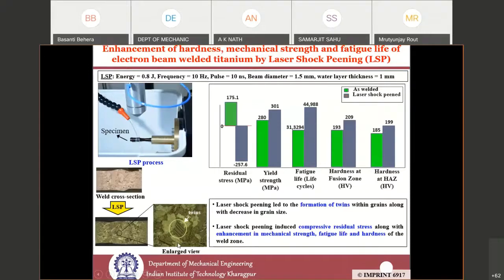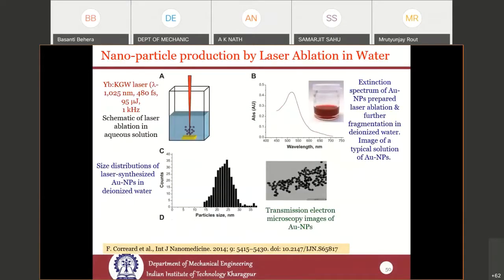Another interesting application of laser underwater is laser ablation in water to generate nanoparticles. Gold and silver nanoparticles are generated using nanosecond and femtosecond laser pulses irradiated in aqueous solution, such as deionized water. The focused laser beam ablates the material, and assisted by water cooling, it generates a lot of nanoparticles in the range of 15 to 30 nanometers. This is one of the very interesting methods to generate nanoparticles of very uniform size.